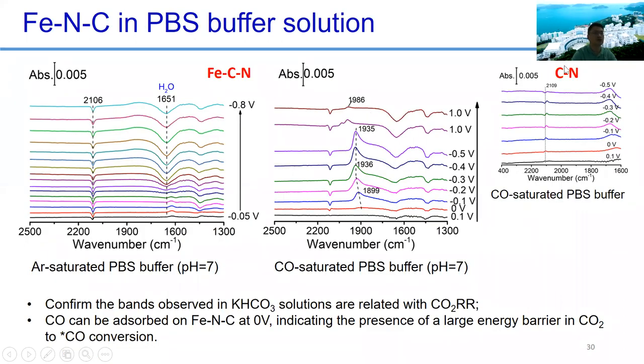And we can also do this on the carbon nitrogen material. For this nitrogen doped carbon without the iron, you don't see any of the band, except this carbon nitrogen bond. So that means the CO is actually absorbed on iron.